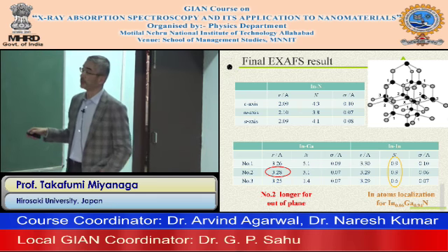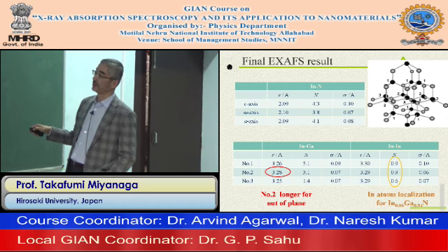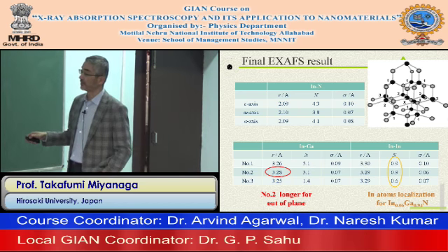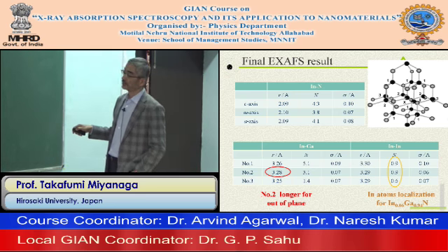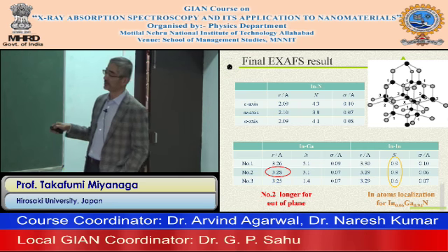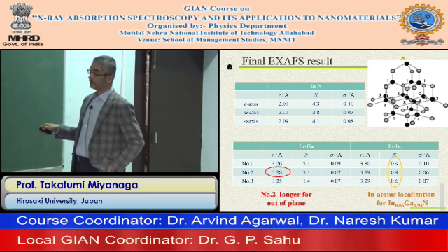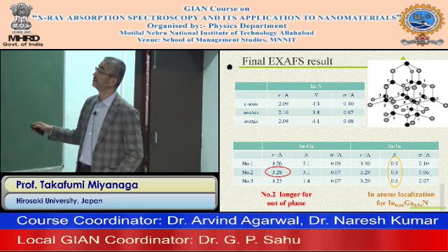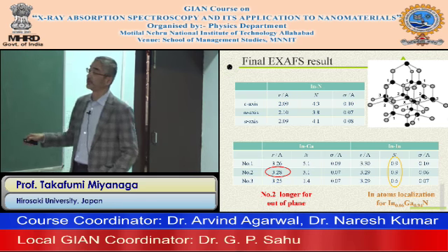But it is interesting to look at the labeled atoms, number 1, 2, and 3, indium, gallium or indium. So as the first step we determined the first atoms, and we also focused on the coordination number of indium. This is a very interesting parameter of this system: 3.26 for number 1, 3.28 for number 2, and 3.25 for number 3.